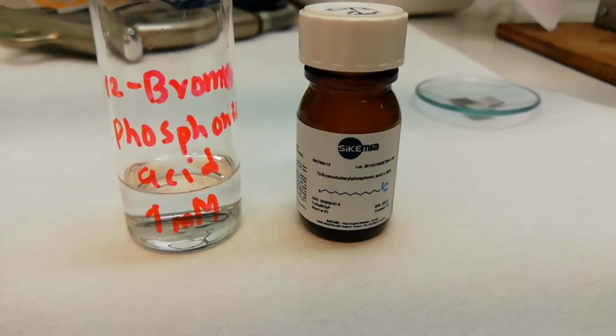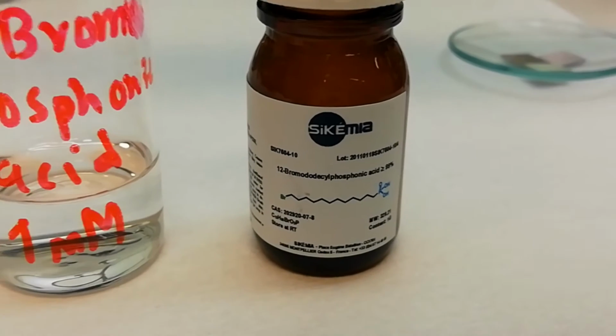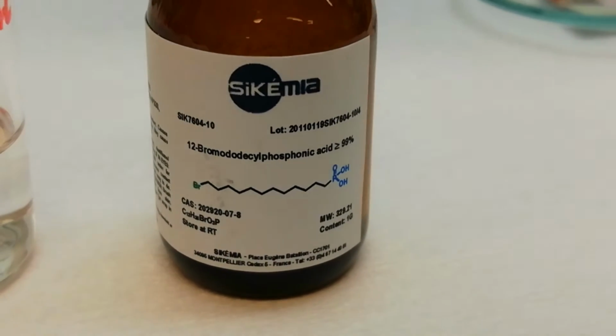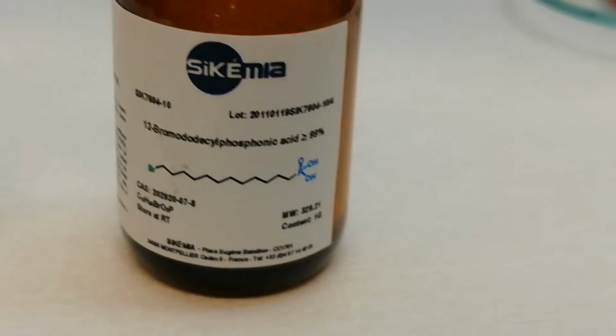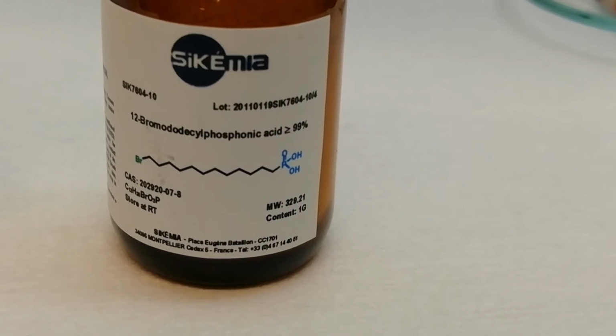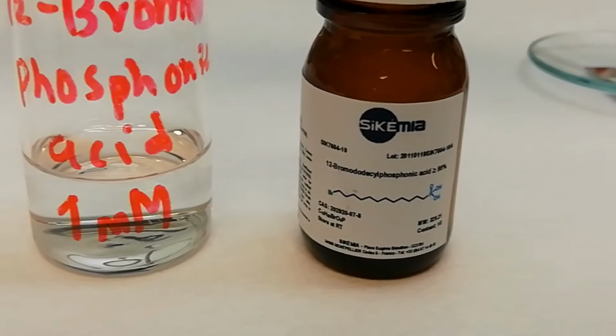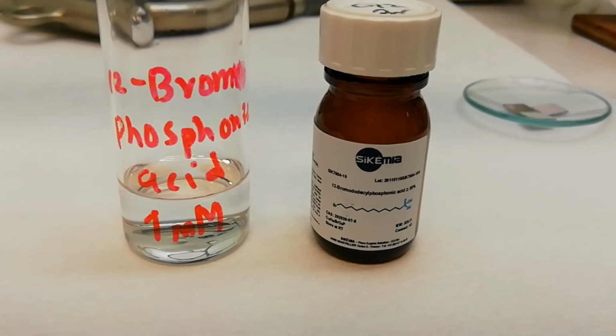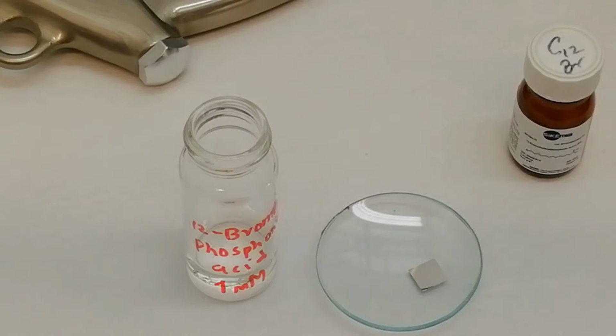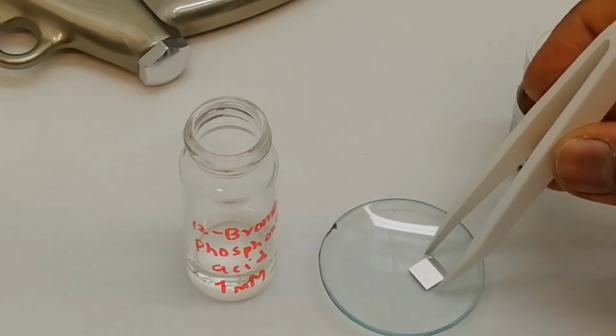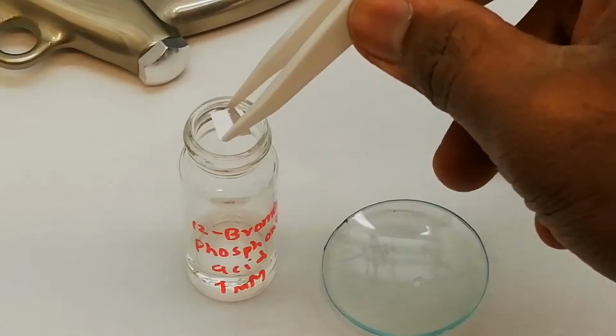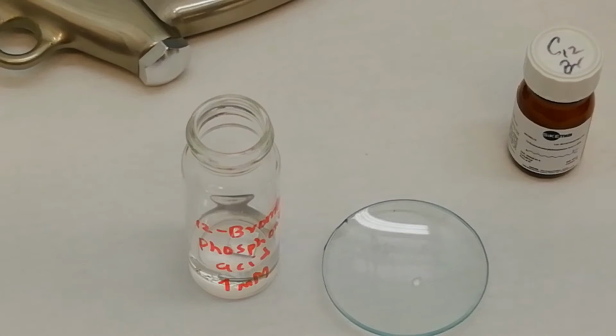Take a 20 ml screw-capped glass vial for surface modification. Prepare the surface modification solution, which is a 1 millimolar solution of 12-bromododecyl phosphonic acid in absolute ethanol. Transfer those dried surfaces into the phosphonic acid solution, and make sure that the mirror side is facing upward.